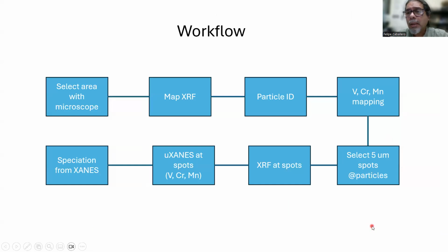This is the workflow in the synchrotron. So first of all, we select an area with a microscope. We observe where we are going to study. The size of the region can be some millimeters wide, something like 10 millimeters wide, so it's relatively large. And then we perform a general X-ray fluorescence map there to observe the general composition of that map. Then we identify particles of interest. Making the map, we can observe, for example, chromium or manganese and see which particles contain one of them or both of them, select them, and then study them.